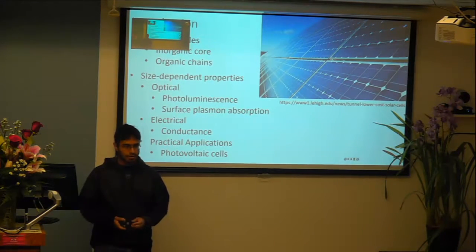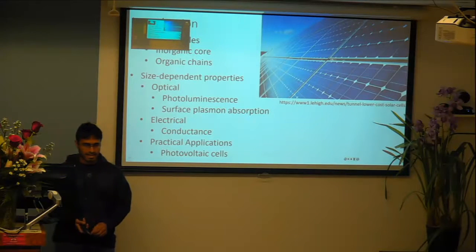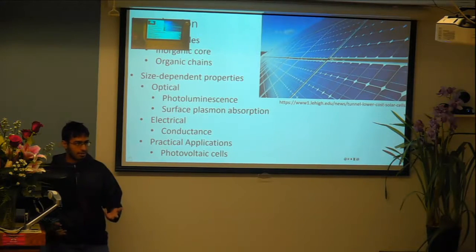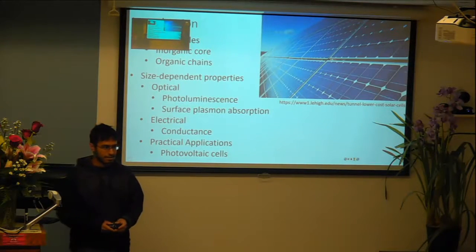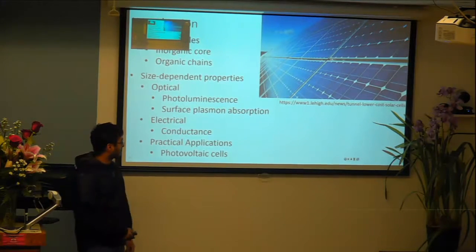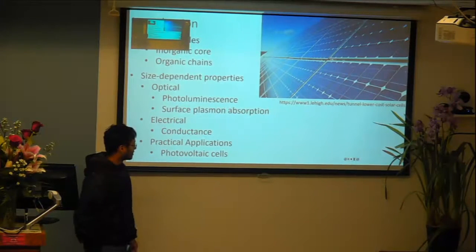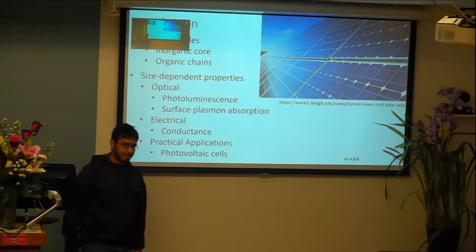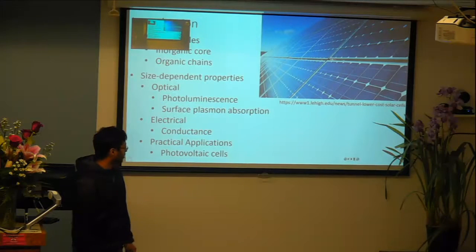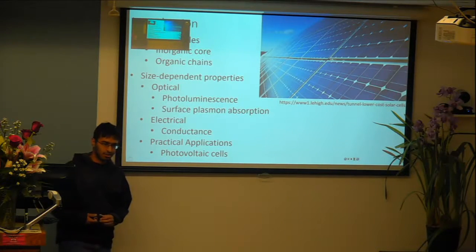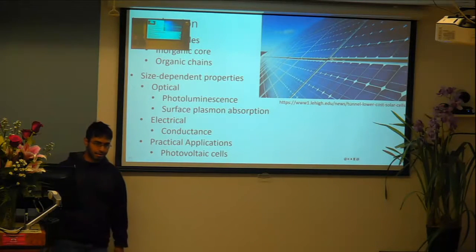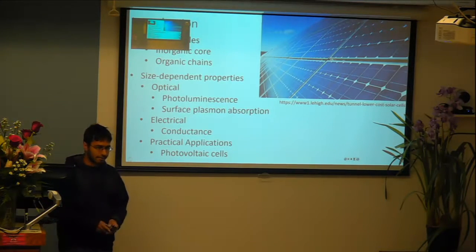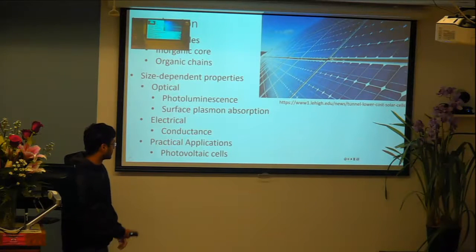Nanoparticles have been shown to exhibit size-dependent properties, in particular optical and electrical properties. Optical properties include both photoluminescence and surface plasmon absorption, and surface plasmon absorption allows the nanoparticle dispersions to exhibit different colors when viewed with different types of experimental apparatuses.